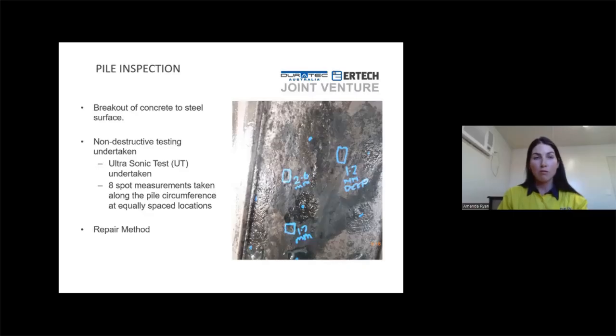So removing the concrete, we did a concrete breakout, exposing the steel, and then we undertook a non-destructive test called a UT test, ultrasonic test. It was taken on 8 spots. Measurements were taken along the pile circumference and equally spaced locations. And with the results from this, we proposed it to the client, and they proposed a repair for each pile.